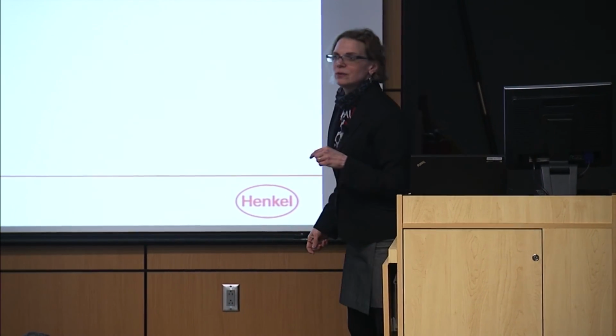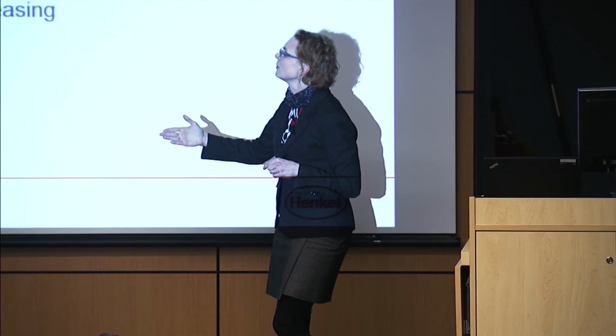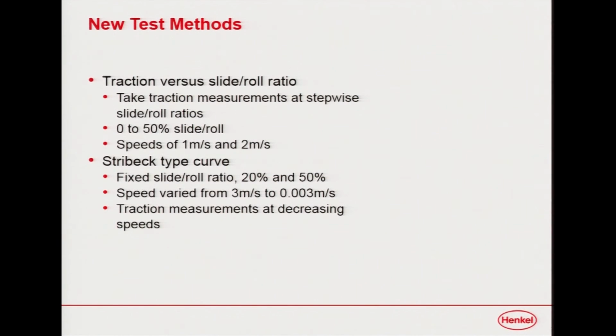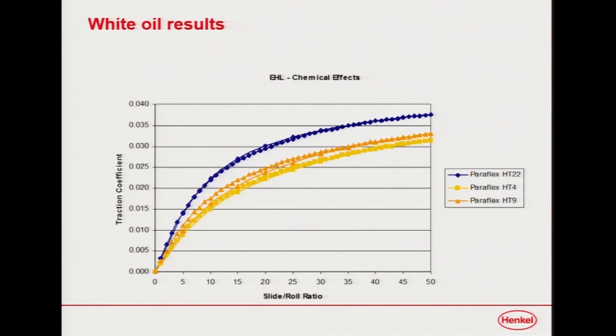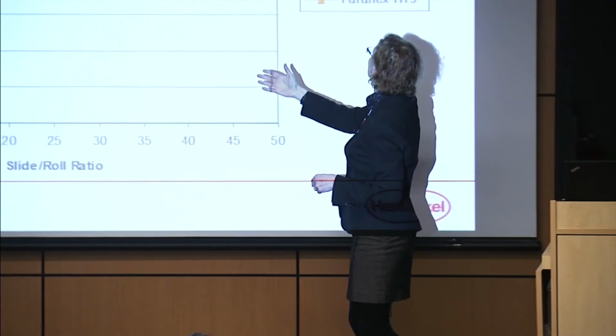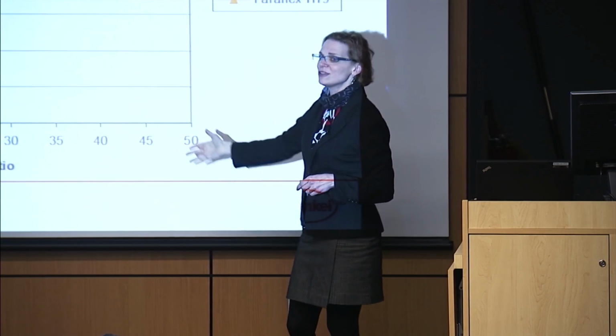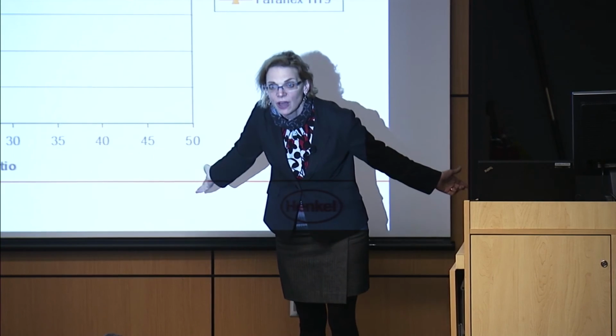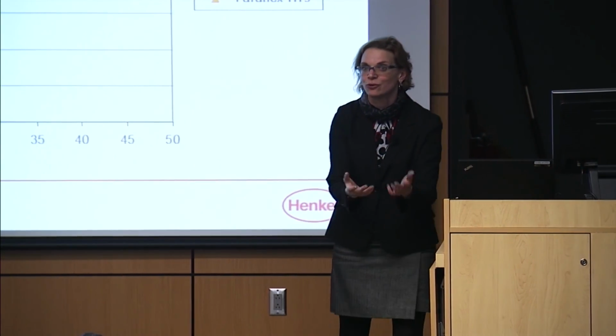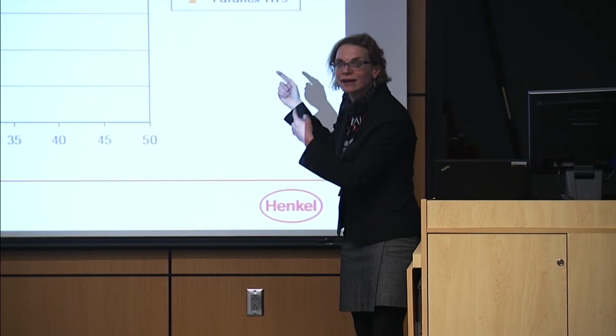What we did was we looked at something called traction versus slide roll ratio and a Stribeck curve, and those are fancy tribology terms that you don't need to know very much about, but you do need to know that when we put a Newtonian fluid in there, it produces these beautiful stacked up curves. It says, oh, hydrodynamic lubrication. Perfect, pure hydrodynamic lubrication. And as the viscosity goes up, the traction or the friction coefficient goes up, because what is viscosity? It is the resistance to fluid flow. That is the frictional contribution of the material in the contact.